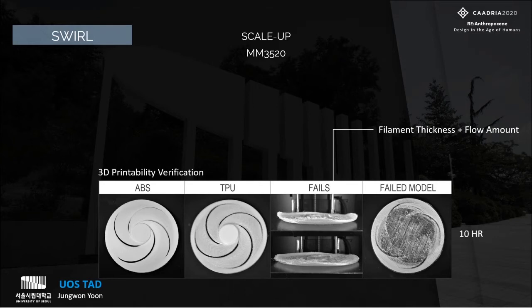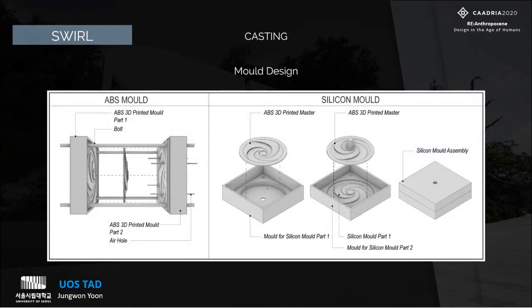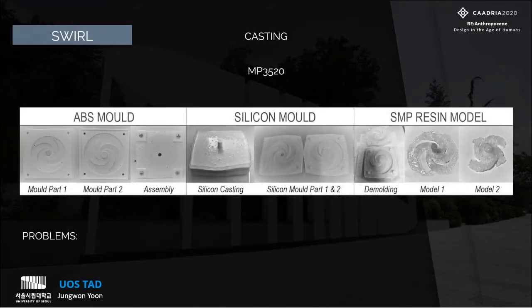Without resolving problems by human surveillance and support, it takes 10 hours to print the 150 mm model, which is not desirable in rapid prototyping. With the concern and doubt on 3D printing, we conducted SMP resin casting experiments. Molds were made in 2 different materials and processes. However, the SMP resin models made with the silicon mold showed problems.